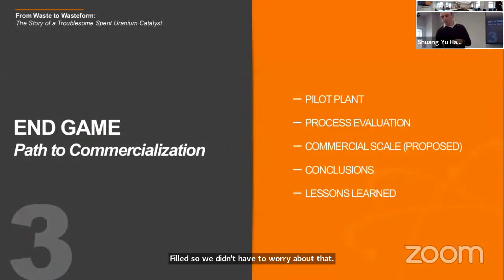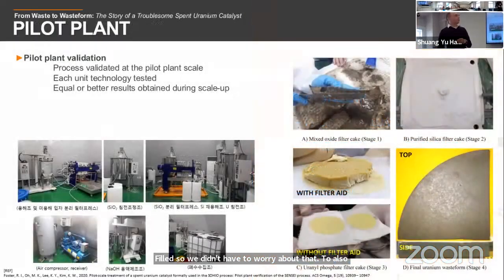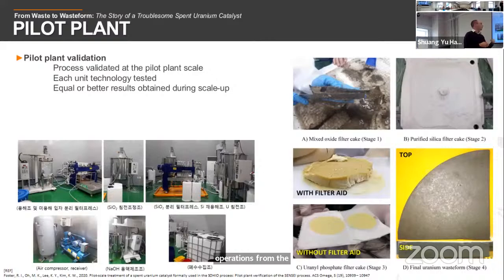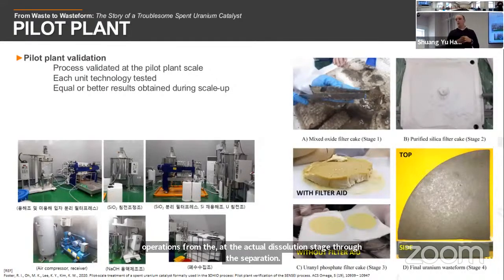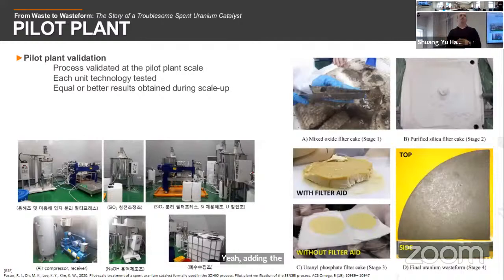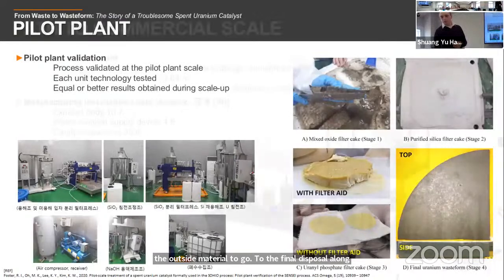So the final stage of this was actually then looking at pilot plant verification, as I've kind of touched on. So we looked at all the unit operations from the actual dissolution stage through the separation, adding the peroxide carbonate to obviously retain the uranium in the effluent before then precipitating that out. And we're actually able to very successfully separate out the oxide material, which would go to the final disposal along with the purified silica at all scales and at the pilot scale as well.